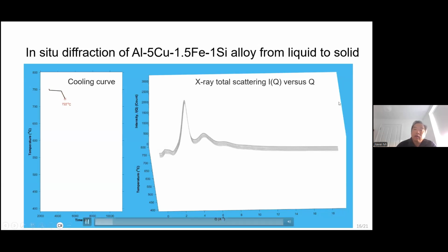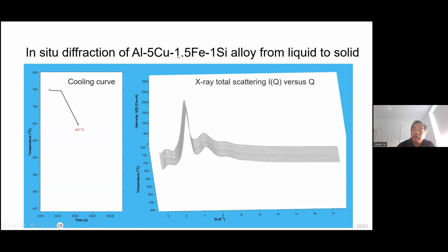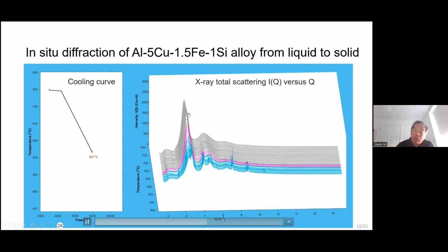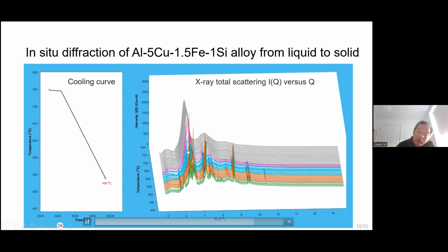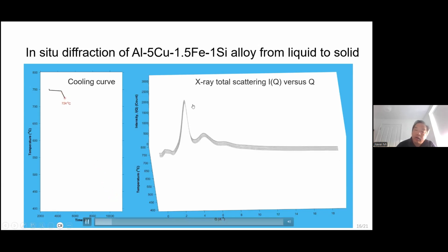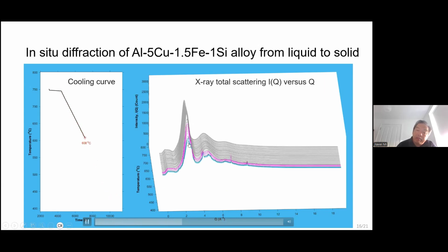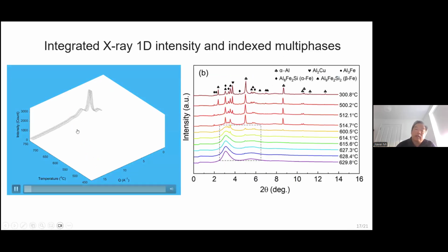So we have to use the so-called total scattering method. In this case, it's particular to this alloy. That's a 4-element alloy, with a composition picked to mimic recycled aluminums. And we watch the change of this intensity versus temperature until, wow, you see a change in the slope of the first peak of the I(Q), and you can see the change of atomic structure, until suddenly a crystal phase appears, which has a peak coming out right here. Using the standard method, we can of course index those different phases.